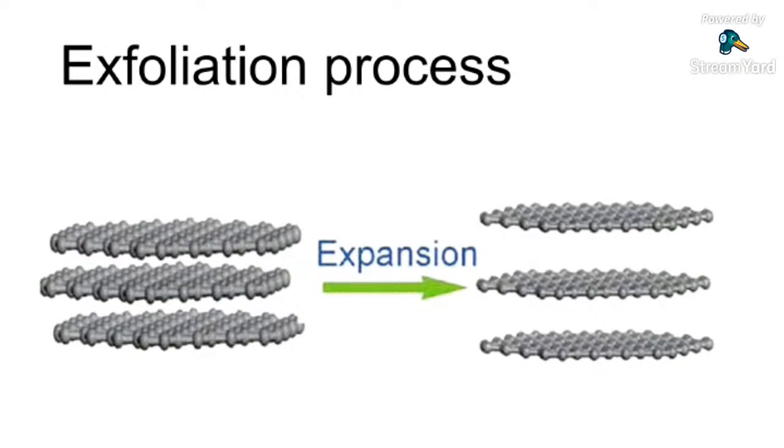How does it work? Well, you have graphite and then you put it in a liquid environment with some solvent. Could be a polymer, an inorganic solvent, or you could use surfactants like those contained in soap, and with the action of the mechanical process, you can separate these graphite sheets and turn them into graphene.